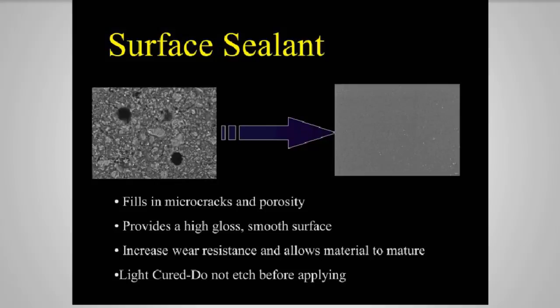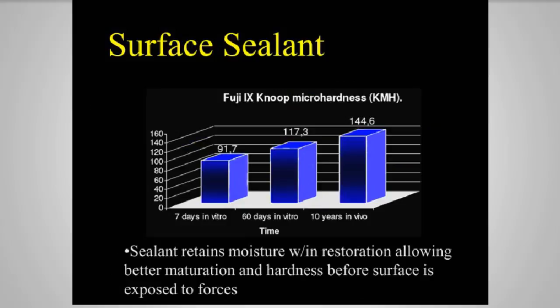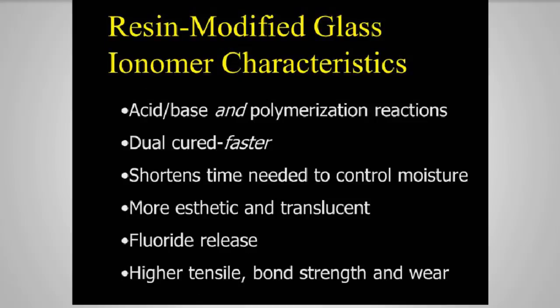And this shows a photomicrograph of the glass ionomer surface and then the surface when the sealant has been applied. What they found is if you put the sealant over top of the restoration, it allows the material to mature. You know, glass ionomer isn't set at the end of the 2.5 minutes. It's still going through a setting process. But by keeping the moisture within it, you allow it to develop ultimately a harder surface with higher micro hardness that will have better wear resistance.